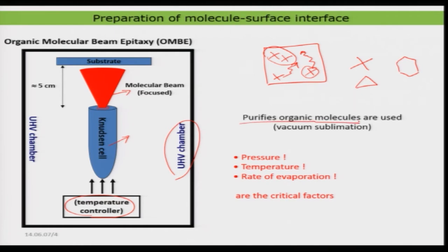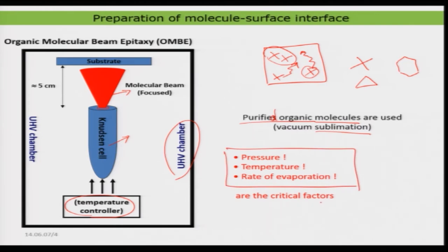You need a highly purified organic molecule present in the Knudsen cell — that is very important. The molecule should also be sublimable; it should not degrade with temperature or melt within the ultra-high vacuum chamber. These are two important conditions to be satisfied. Then the pressure in the chamber, the temperature at which you evaporate, and the rate of evaporation are also very important. If you precisely control these parameters, you can form a beautiful ad layer of molecules.